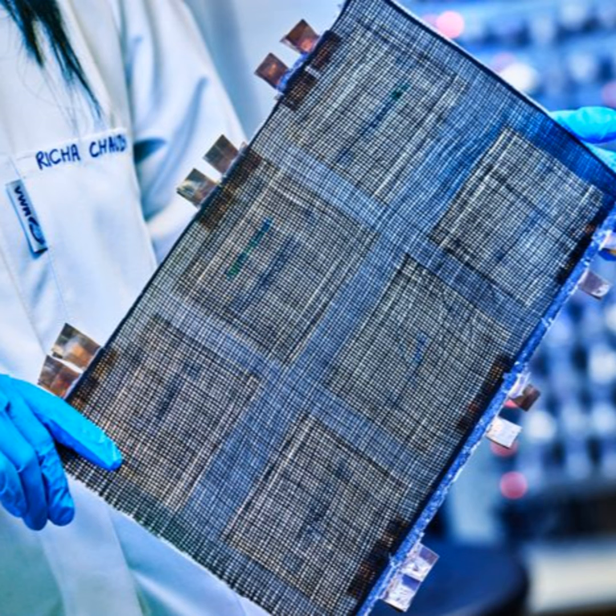But now we have been able to coat carbon fibers with lithium iron phosphate as an active material. We have the carbon fibers as reinforcement and current collectors and the scaffold for the LFP, and then we make a full cell with that, so we can actually get a very high modulus carbon fiber composite battery, and also with reasonable energy density.